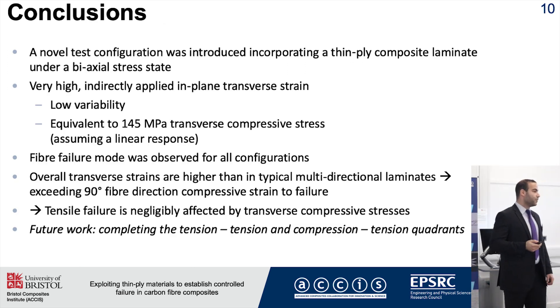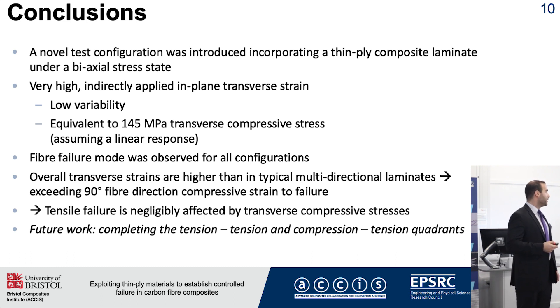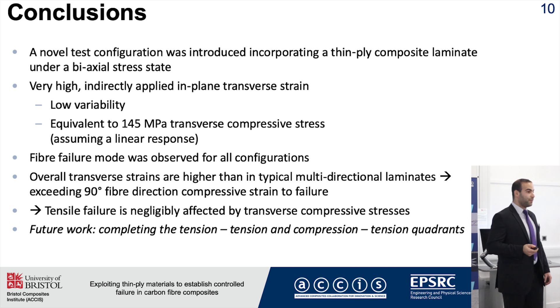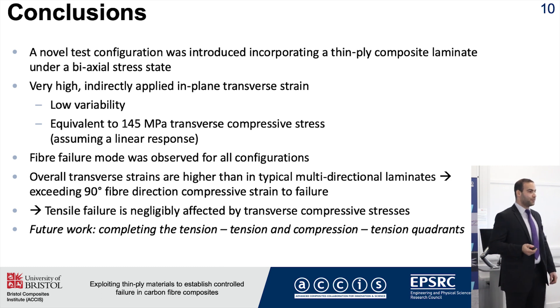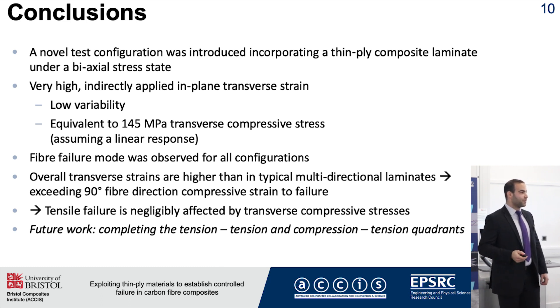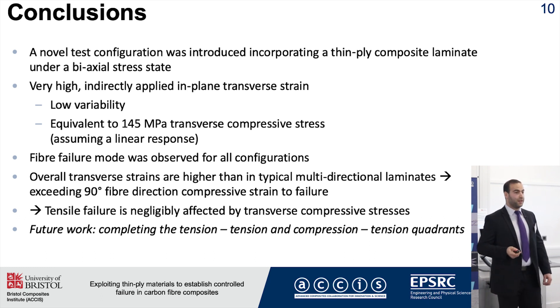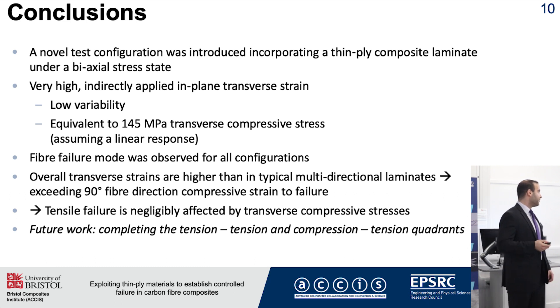To conclude this work package: we developed a novel test configuration incorporating a thin ply composite laminate under biaxial stresses, with very high indirectly applied transverse compressive strain and low variability. We achieved the equivalent of approximately 145 MPa of transverse stress, assuming linear responses. For all configurations, we observed a fiber failure mode, and the overall transverse strains were higher than in a typical multi-directional laminate, exceeding the 90-degree fiber-directional compressive strain to failure. All in all, tensile failure is negligibly affected by the transverse compressive stresses.